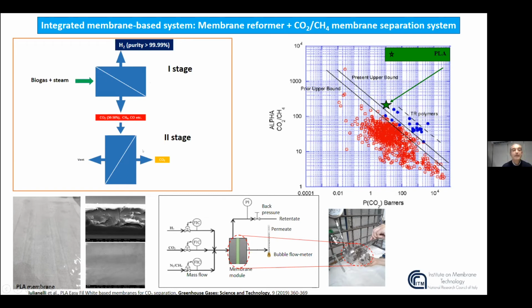biopolymeric membrane module in which the CO2 is separated from methane. And in this regard, we developed a particular process for realizing polylactic acid membranes as biopolymeric membranes, which were particularly selective to CO2 versus methane. This is the scheme of the experimental setup and the picture of the real planar membrane module.